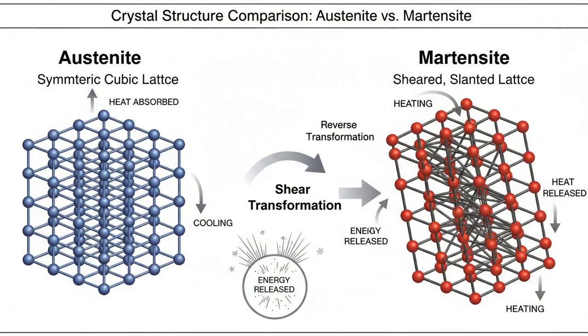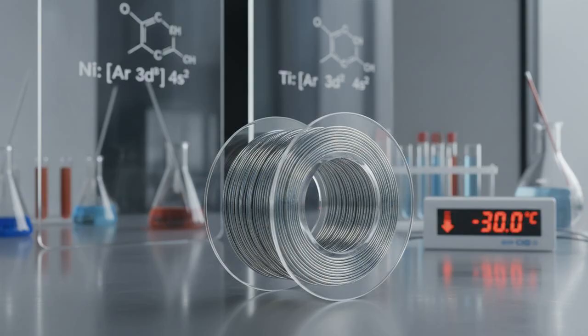When you release the stress, the material wants to return to the high-entropy austenite phase. It sucks thermal energy from its surroundings to fuel this atomic reshuffling, creating a cooling effect. This is the latent heat of transformation, the solid-state equivalent of boiling and condensing a liquid refrigerant. Now, not all metals can do this. If you stretch a steel bar, it heats up slightly due to thermoelasticity, but the effect is negligible.